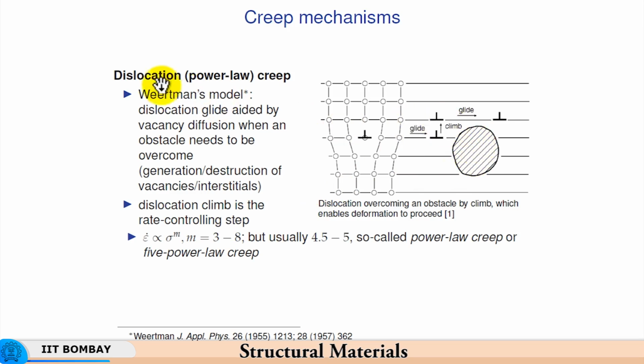So, in case of power law creep, the dislocation climb is the rate controlling mechanism, which means that if you are using the activation energy, you would use the activation energy for dislocation climb. If you are talking about Coble creep or Nabarro-Herring creep, then the activation energy for diffusion through the lattice or the activation energy for diffusion along the grain boundary will have to be used for the Arrhenius equation. So, that is the difference it makes. The mechanism here involves dislocation climb as a rate controlling step. Earlier mechanisms involved diffusion as the rate controlling step.